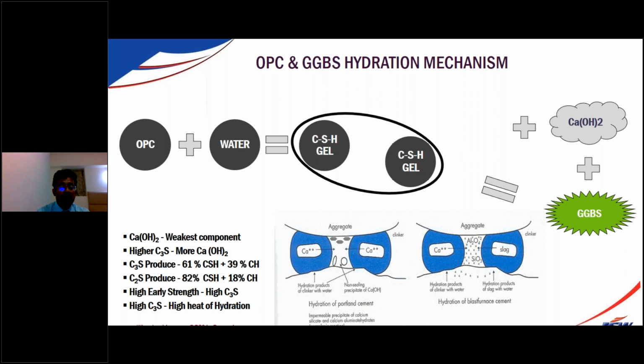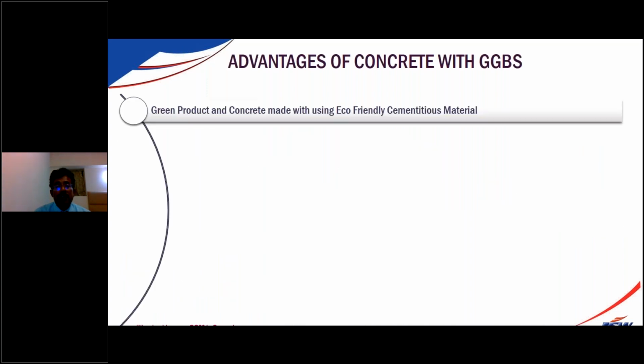So as we go to higher grades of cements, you are going to have more calcium hydroxide. That is very detrimental to the concrete. What I am telling you is that you have to reduce the calcium hydroxide in the concrete matrix. That is only possible by partially replacing the OPC content using GGBS or fly ash.